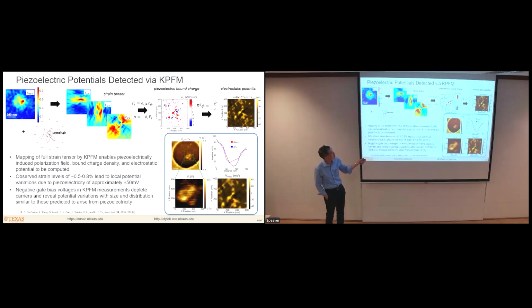And you can see that these bound charges have magnitudes up to a few times 10 to the 10th, which is about what we would expect. We can then take those bound charge distributions and solve Poisson's equation for the corresponding electrostatic potential. We get this. And then if we go back and look at the Kelvin probe microscopy measurements, but now at negative gate bias voltage, where carriers are depleted, so that you actually unscreen the piezoelectrically induced bound charges so that they can be observed, we get this type of surface potential map over here.